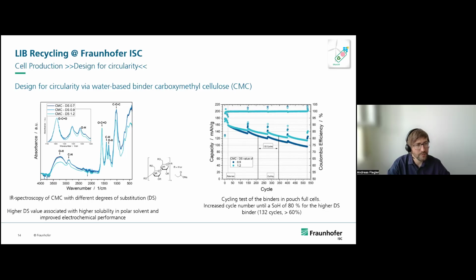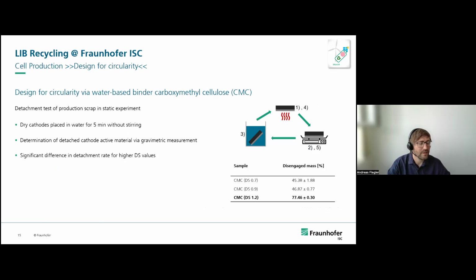And this higher degree of substitution is also very good in the recycling process when we put the electrodes into water without stirring or something like that. So we get a detachment of the electrode with a higher degree of substitution. So this is, in our opinion, a huge research area: to develop new binders which can be easily recycled and extracted out of the recycling step.